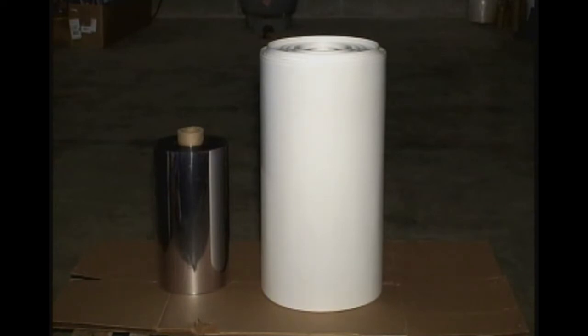thick. The roll width increased from 20 inches to 30 inches wide. The roll length increased from 600 lineal feet to 900 lineal feet. The roll still weighs about 100 pounds, but the volume has expanded about 5 times. In other words, the density is about 20% relative to the original solid material.